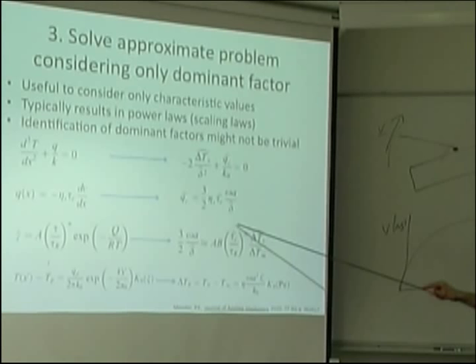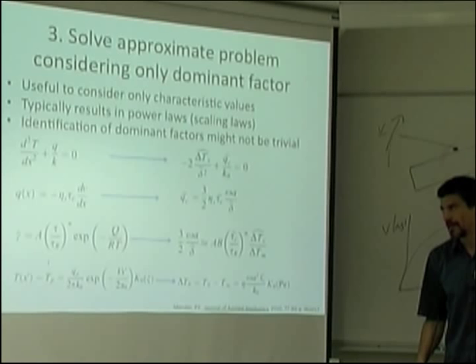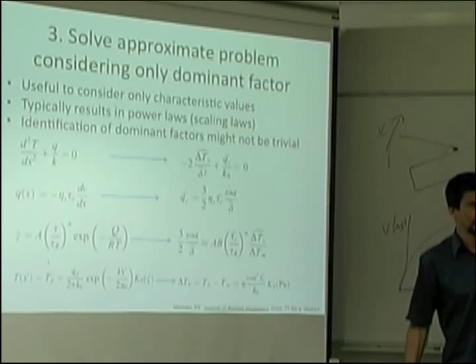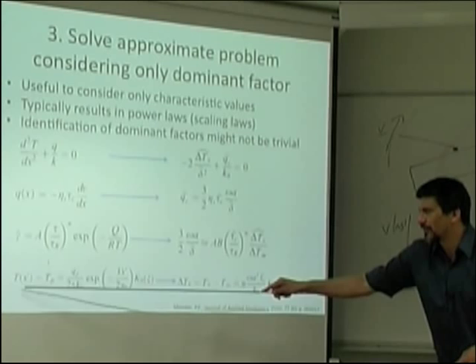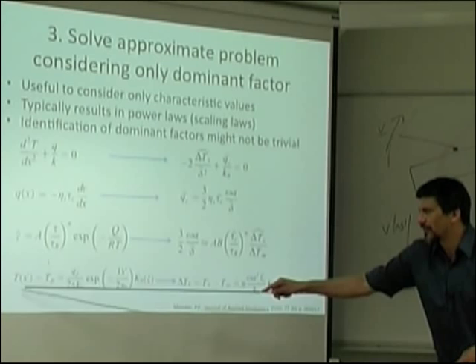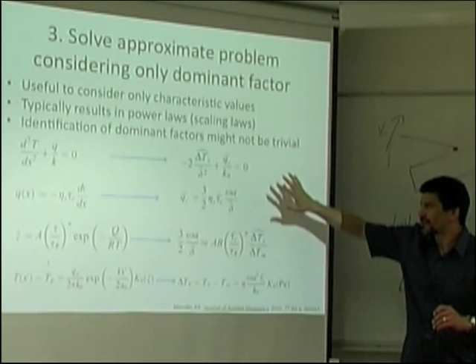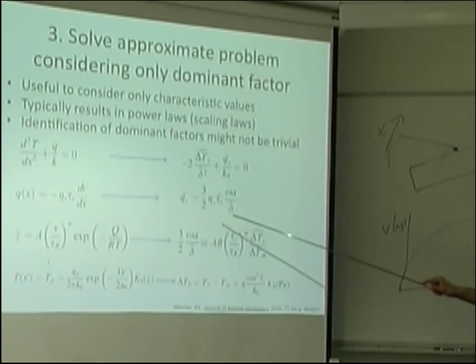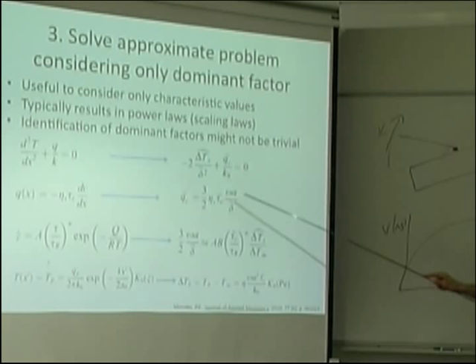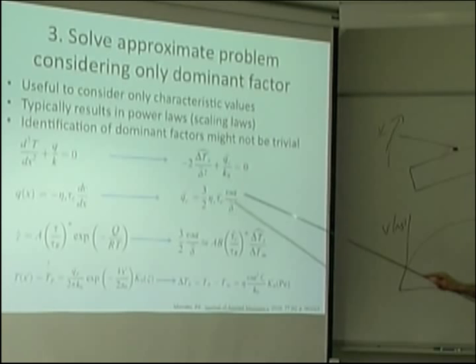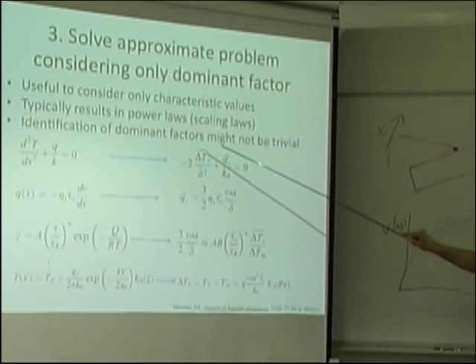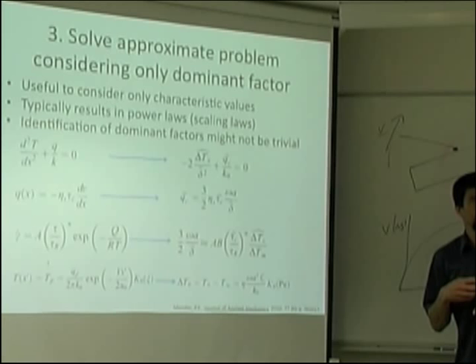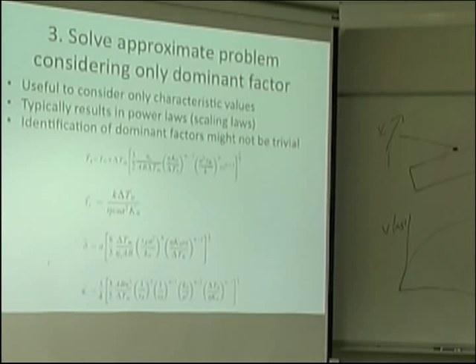Based on the hypothesis I mentioned at the beginning, which I have not tested, so you have to take a moment of faith as far as this slide goes, I can write my heat transfer equation this way. That's a very simple equation. Even if this is not linear, it's still very simple. Now, temperature for this problem is a pseudo steady state, so time doesn't matter. With the simplifications, maybe you end up having a radial symmetry and end up having only one coordinate. So temperature depends on x. My field is temperature as a function of distance, whatever that distance might be. I don't care about temperature as a function of distance. What is my maximum temperature? That's what everybody talks about. That's when this colleague of mine melted the titanium. The problem was the maximum temperature. The whole evolution of temperature with distance, who cares? He melted it. So I can normalize it following the guidelines of this publication, and you would end up with this. This is a differential equation. A simple one, but differential. This is an algebraic equation.